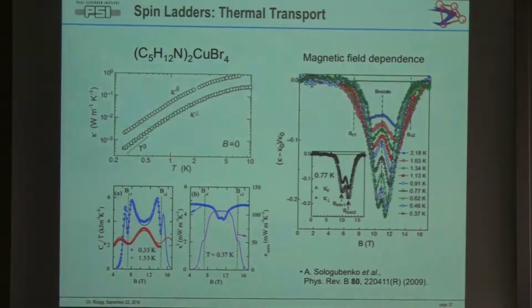In principle, the conductivity is not infinite without impurities. No, not because we are at somewhat finite temperatures, with the density you have for the spinons. It's because of umklapp. Yes. So this is possible, of course, in any case. But now the way this couples to the magnetic field, that's now the question, because in the spinon picture you get incommensurabilities which are field dependent, and maybe the umklapp scattering does this in a different way, but we didn't.